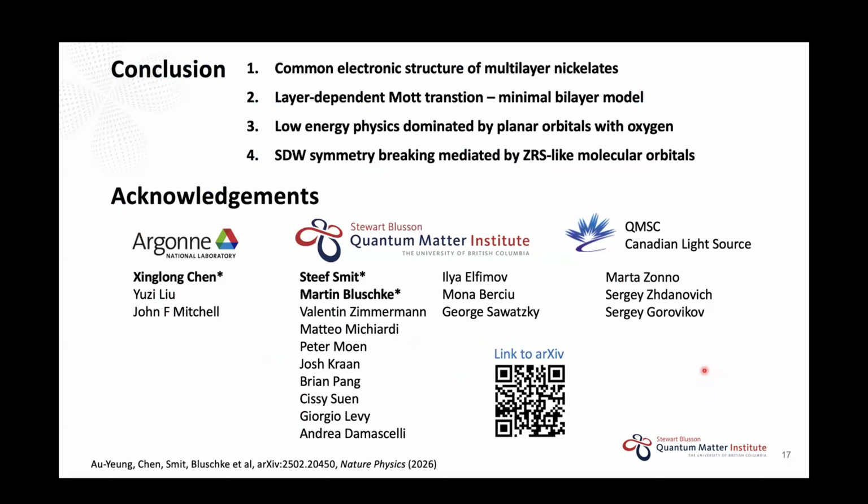Okay, so this is the end of the presentation. Our conclusion is that the nickelates share a common electronic structure. I'm talking about the multilayer nickelates. And the important reason is that there is a layer-dependent Mott transition, and the minimum model is a bilayer model. The low energy physics is dominated by planar orbitals of the oxygen, and the one that is responsible for the spin density wave is the Zhang-Rice singlet (ZRS) molecular orbital.